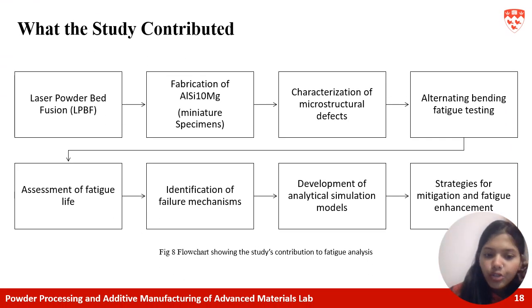So moving on to what the study contributed. First of all, we had the fabrication of the alloy with the additive manufacturing technique of laser powder bed fusion. And they fabricated miniature specimens, and these were characterized by different techniques for microstructural defects. And these specimens were then subject to alternating bending fatigue testing. And then an assessment of the fatigue life was done. Then various failure mechanisms were identified, and later they developed analytical and simulation models and strategies to mitigate these defects and to enhance the fatigue life.